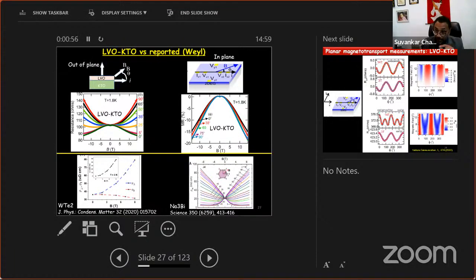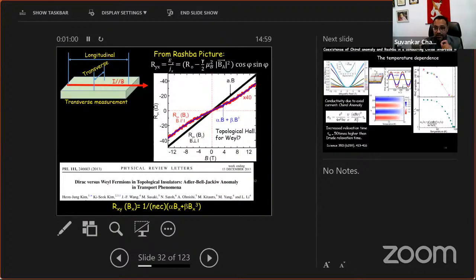I completely agree with that. But at the same time, what bothers us is this. This cannot be explained from any known physics, because when you apply a magnetic field along the direction of current, there is no reason that you should see the transverse resistance, until and unless in your equation of motion you have a Berry curvature term. So there must be some kind of Berry curvature coming from something which is giving rise to this p cross sigma type term, right? So this is why we are at least thinking about Weyl. I'm not saying at all it is Weyl, but my point is, there is some kind of Berry curvature, and to know this, we must know the band structure of this material.